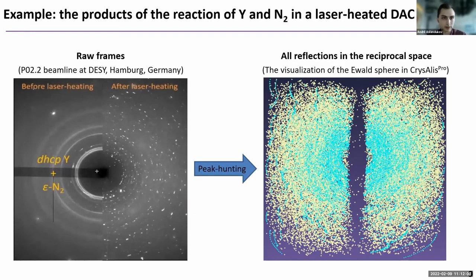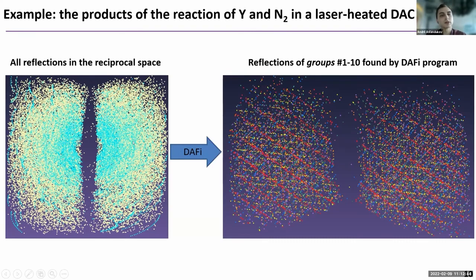So now let's look at an example. A piece of yttrium and nitrogen was loaded in the diamond anvil cell. Then the cell was laser heated at the P02.2 beamline at DESY. And as you can see, after laser heating, a novel phase crystallized. We collected single crystal X-ray diffraction data in a plus minus 38 degree omega range. And the peak hunting procedure in CrysAlisPro found almost 70,000 reflections. Some reflections here were filtered by DAFi, so they correspond to diamond and other artifacts.